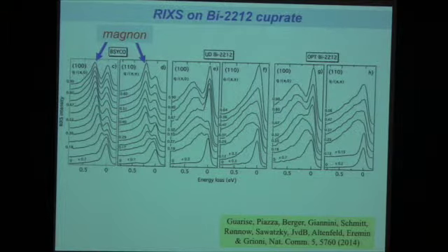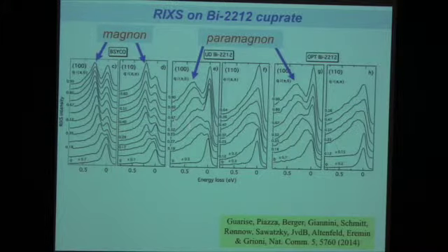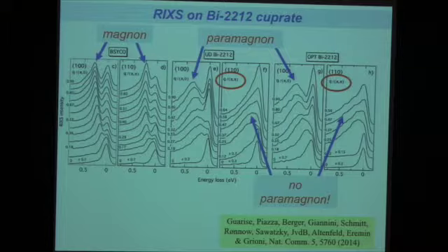That's all right. Now let's look at the underdoped system and look at the dispersion in the (π, 0) direction. In the (π, 0) direction, yes, there's a paramagnon. Even if we go to the overdoped system, again, in the (π, 0) direction, there's a paramagnon. If I go to the (π, π) direction, however, I would not see much evidence. There is some spectral weight here, but it's really not the paramagnon that you see in the (π, 0) direction.